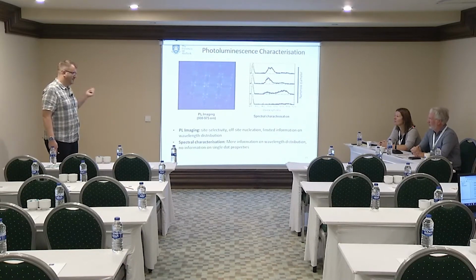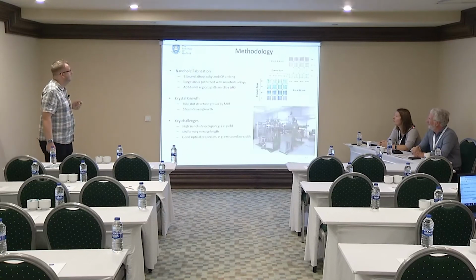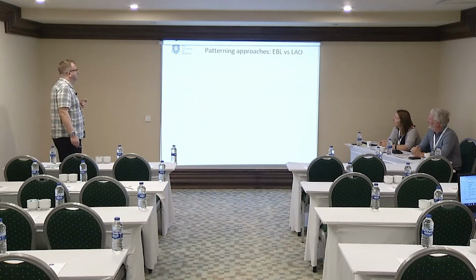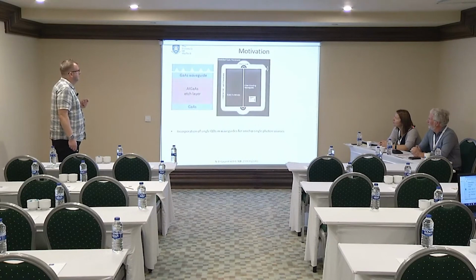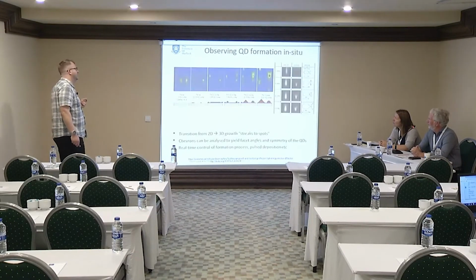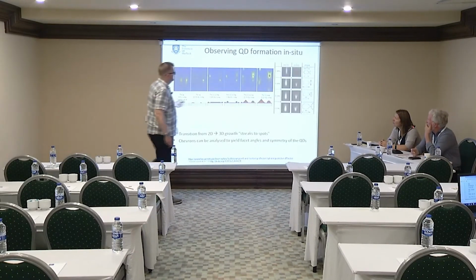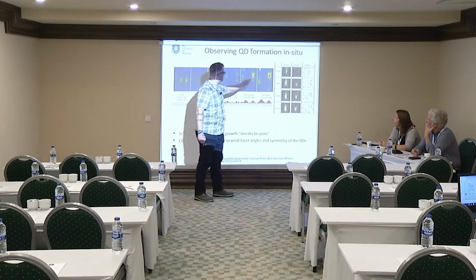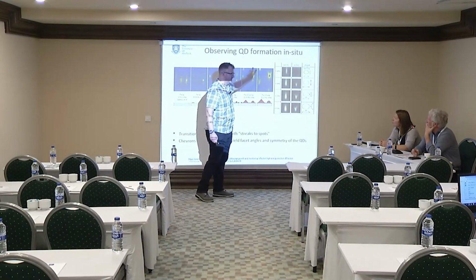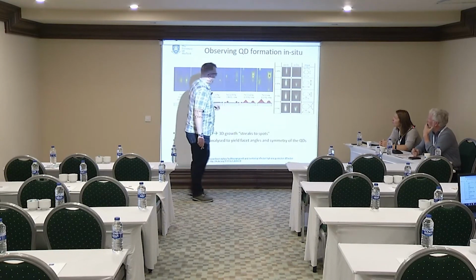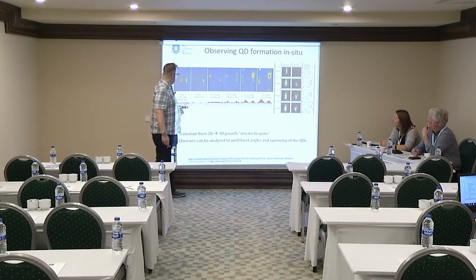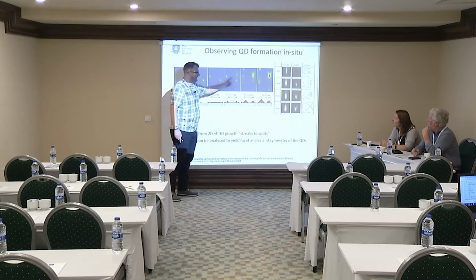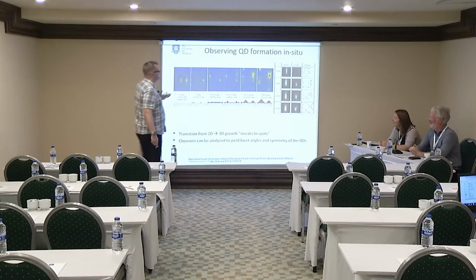When you're trying to grow these very low density dots, I can just see the first spot appearing, if you like. To actually see the change in the facet angle, and the other thing you can see is when the third line appears, that gives you an indication that you have a lot of dots. But in terms of where we want to be for measuring, it's between here and here, which on any projector screen is no change.